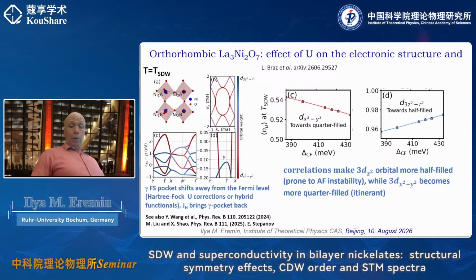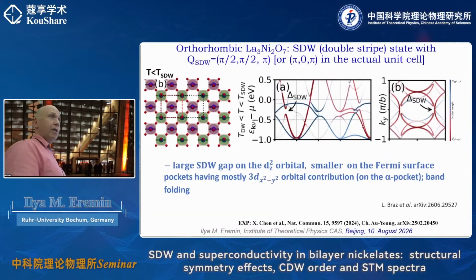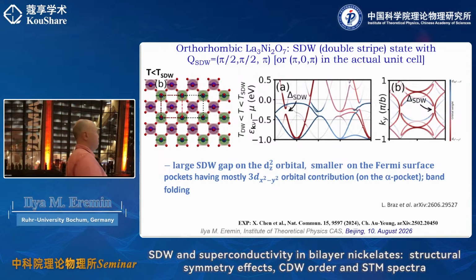Okay, good. So once you do this, you know already that before a spin density wave state, in this case, it's a weak coupling calculation, and the instability is driven by this pi over 2, or in this unit cell, it's a 0 pi. And indeed, you develop such an order, which is a spin density wave order. And you see this Fermi surface reconstruction that appears due to the formation of this 0 pi order. You can see that the large gap is developing on the dz square orbital, because it's more correlated. But you still have a residual Fermi surface because it essentially comes from the dx square minus y square orbital contribution, and there is a band folding. Okay, so you also can identify where the spin density wave gap might open exactly.